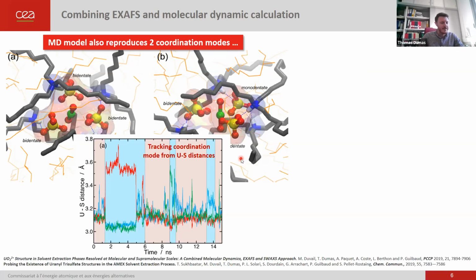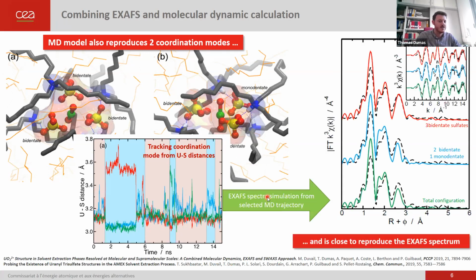And in the molecular dynamics time scale, by measuring the uranium sulfur atom distance, you can look at when you have one configuration or the other. When you have 3 bidentate sulfates, you have the 3 uranium sulfur atom distances that are the same. And then sometimes, here in the blue area, it splits and you have the second configuration, and then it comes back and again like that. Okay, the last thing you can do from this molecular dynamics calculation is you can just take some snapshots of the trajectory of uranyl,